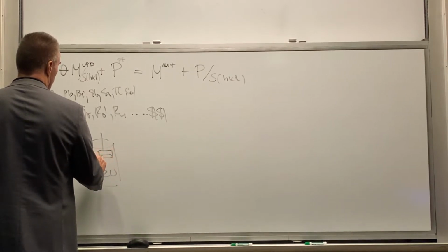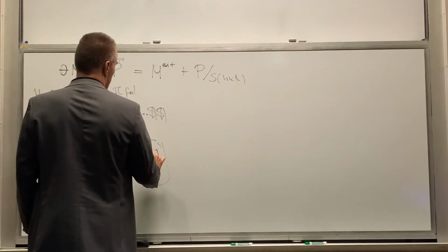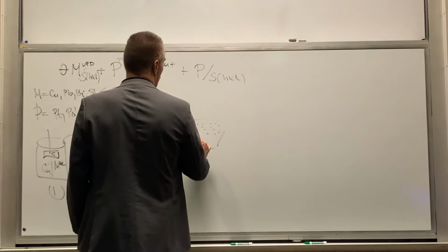Then the second step will be to rinse this from any residual solution where we have the M UPD monolayer on the substrate S. And then to go to a third solution which contains P plus ions. Stick this, and what's going to happen is that there will be surface redox replacement, and eventually what we will end up with is the substrate surface which is decorated with two-dimensional clusters, or eventually a completely covered surface with a 2D P deposit.